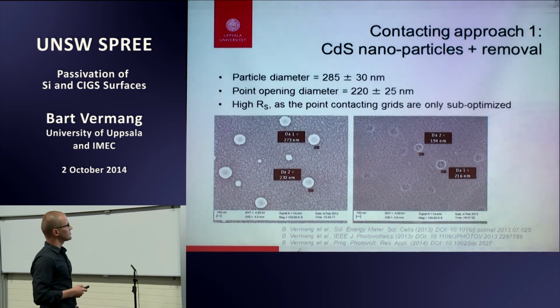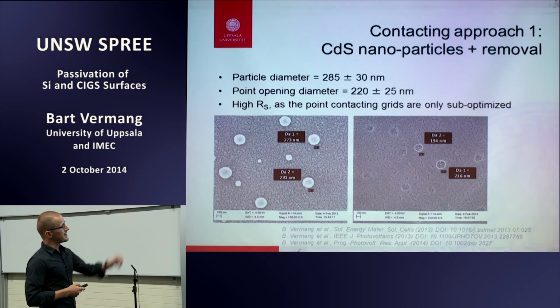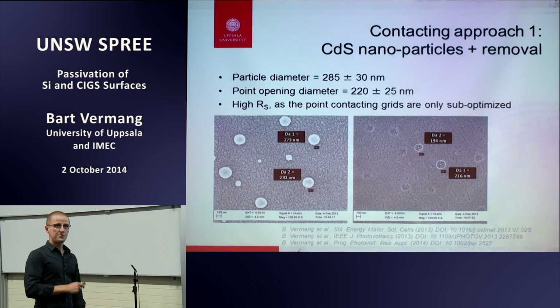Here you have a few top-view pictures, where at the left you see those cadmium sulfide nanoparticles, and on the right you see the same top view after removal of the nanoparticles, and you see some openings of around 220 nanometer. Those cells, the advantage is it worked fine. The disadvantage was you lose a few percent in fill factor, because in the end it's random where you have the nanoparticles, so it's only sub-optimized contacting grids.